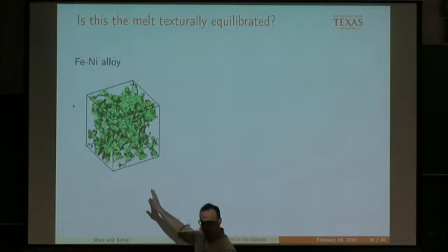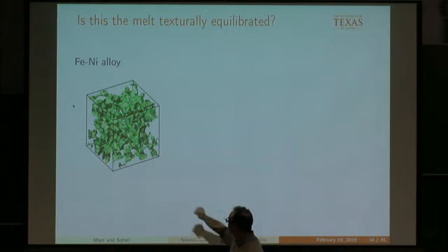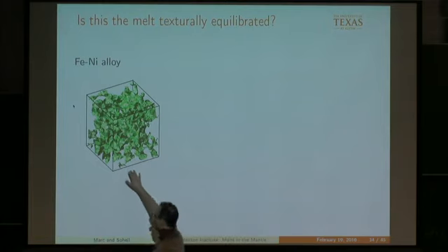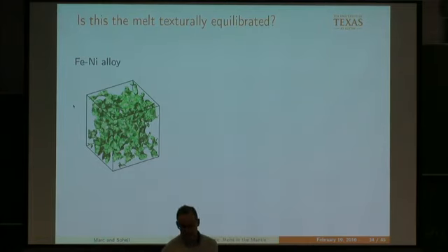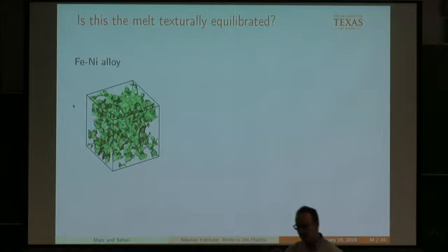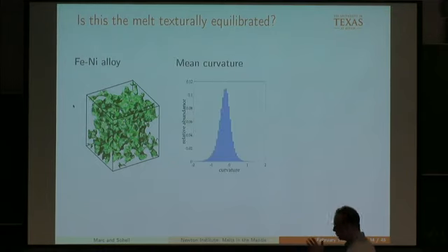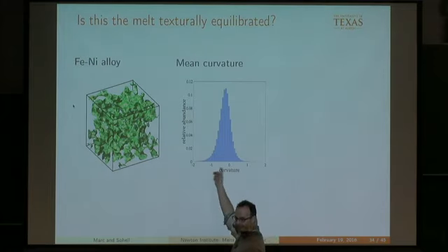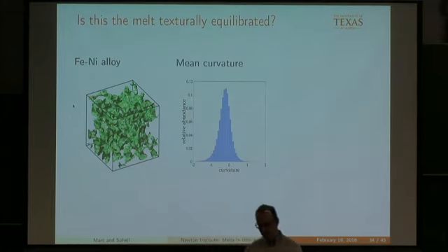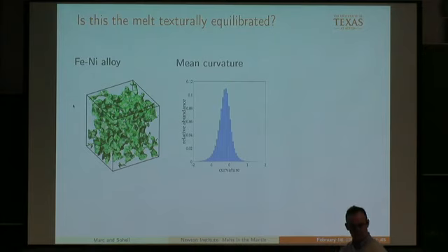And then you can calculate the curvature and plot it on the surface, and you see that it's largely green, which means it's largely the same curvature. There are some speckles, but those could simply be from the fact that you're interpolating the CT image, which is a bunch of cubes. And if you plot the mean curvature, it's actually surprisingly Gaussian. There's a preferred curvature. Now, I don't know if this is an acceptable spread in the curvature, but clearly there's a preferred curvature to the system, which is kind of nice. And you could use that to argue that it's trying to have a certain mean curvature.